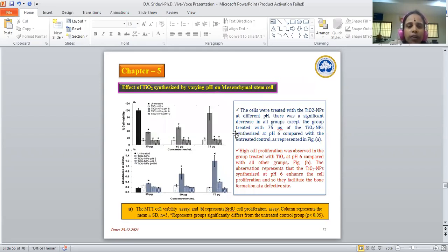This slide shows the effect of TiO2 synthesized by varying pH on mouse mesenchymal stem cells. Figure A shows the MTT cell viability. Figure B represents the BrdU cell proliferation assay. Initially, the cells were exposed to 3 different doses: 25, 50, and 75 microgram per ml. It was observed that when cells were treated with TiO2 nanoparticles at different pH, there was a significant decrease in all the groups except the group treated with 75 microgram of TiO2 nanoparticles synthesized at pH 6, when compared to the control, as shown in figure A.